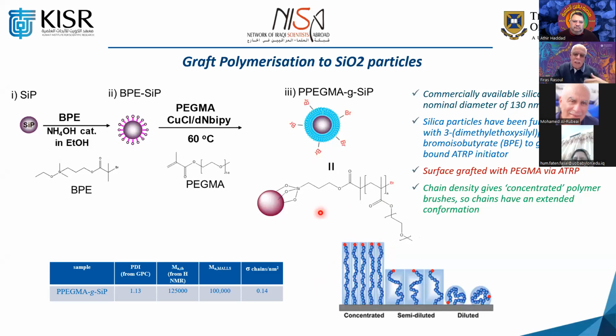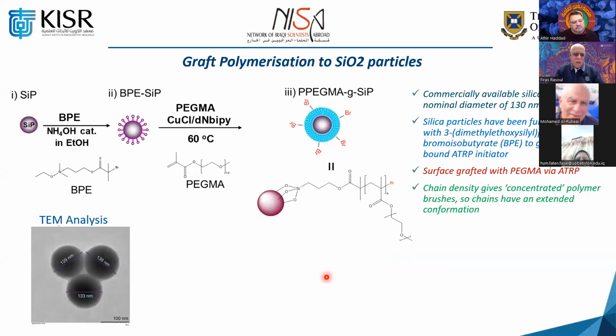functionalization. While with a lower functionalization or lower polymerization, using a lower concentration in the first step, you will end up with a semi-diluted or diluted brush. If they are diluted, you find all the chains fold onto the surface, and they are not very easily accessible to do further polymerization and further reaction. So this is one of the disadvantages. However, we found that a higher concentration is good. But again, higher concentration has a disadvantage because of the excimer formation. So this is another issue which we think of.